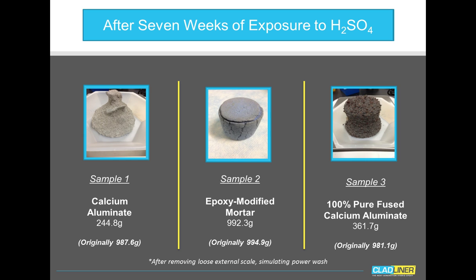So after 7 weeks, and this is where the study was concluded, this is what the final samples looked like. Calcium aluminate was down at 244 grams. The epoxy modified mortar was down at 992 grams. And the pure fused calcium aluminate was down to 361 grams. As you can see, the original weights are listed at the right below the actual current weights.